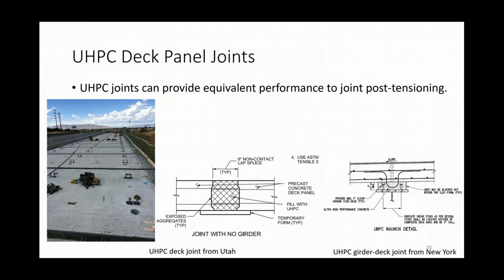Okay, the second example with UHPC applications is deck panel joints. So these would be precast concrete deck panels. UHPC, as you know, is much more expensive than conventional concrete. So most of the applications you see would be small volume applications. So this is an example of that. So precast concrete panels, either between the two panels or between the panel and the girder, you can use UHPC. And we heard during the workshop from Utah and New York, and they both reported that when they did use UHPC joints, they actually got pretty much equivalent performance to post-tensioning these deck-to-deck joints. So if post-tensioning is not a desirable construction method, UHPC seems to be a little bit easier.